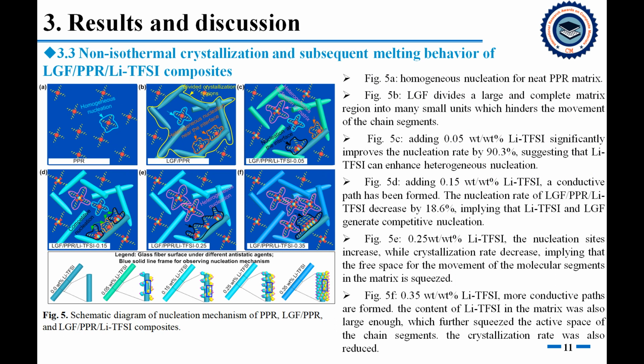According to these parameters, a schematic diagram of the nucleation mechanism is given. Homogeneous nucleation for the neat matrix. Long glass fiber divides a large and complete matrix region into many small units, which hinders the movement of the chain segments. Adding 0.05 weight% organic salt significantly improves the nucleation rate by 90.3%, which suggests that organic salt can enhance the heterogeneous nucleation.